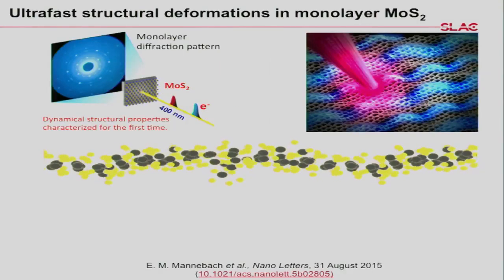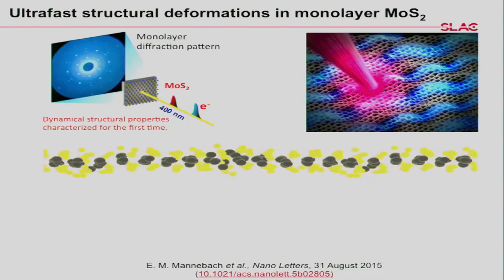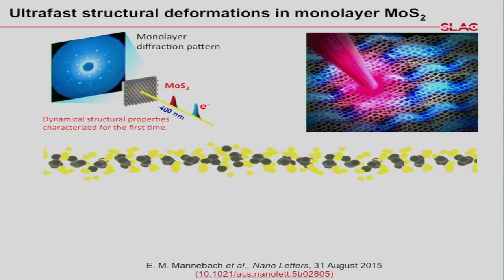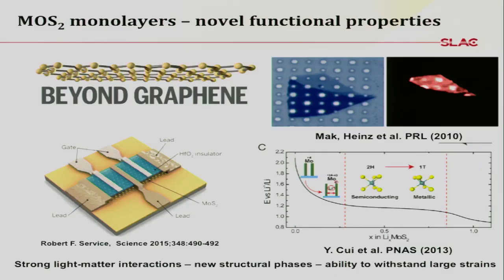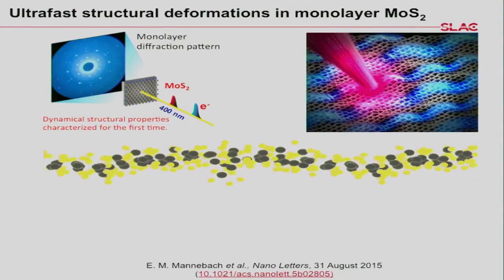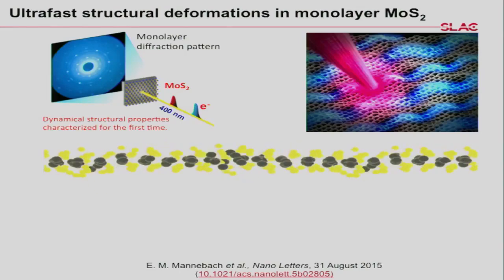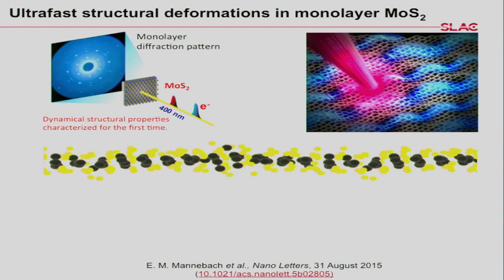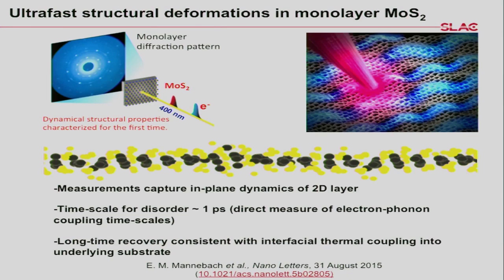So the property we look at is a MoS2 single monolayer. We look at the light shining on these materials. Basically, that's the material, and here are the diffraction patterns. And we want to look at how, when light shines, this monolayer changes by deformation, because you can control the electrical and optical properties. So we observe there are in-plane and out-of-plane deformations.